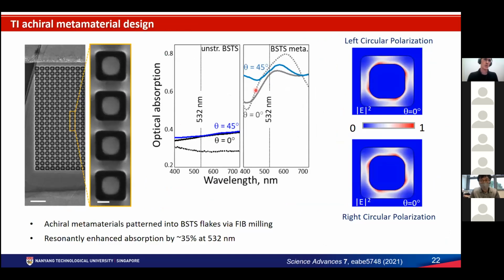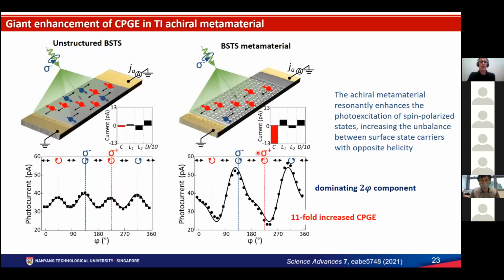So our working hypothesis was, if we nanostructure the material now, first of all, will the surface state survive? Second, will the absorption that is dictated by the metamaterial design, where as you can see here we can obtain an increase, like a doubling of the absorption, have an effect on selectively exciting and selectively absorbing spin carriers that are sensitive to the circular polarization of the light? So we decided to start with a metamaterial that does not have any optical photonic chirality effect, because we want to start by observing something that reacts the same way to left and right circular polarized light. And we did the experiment on an unstructured BSTS flake first, and then we followed on the same flake by nanostructuring the BSTS with a metamaterial made of square rings.